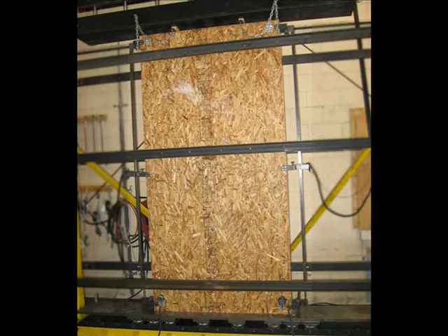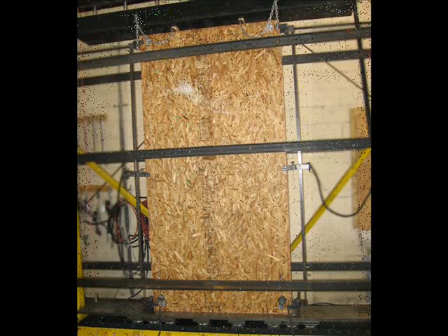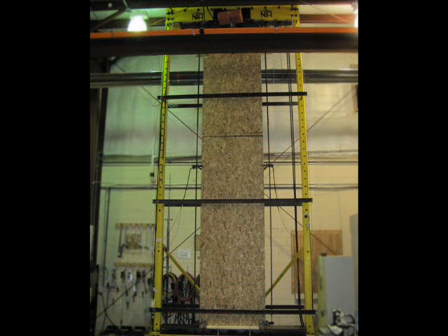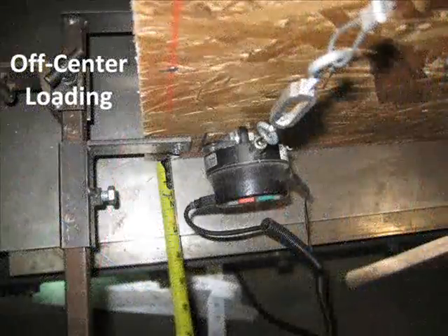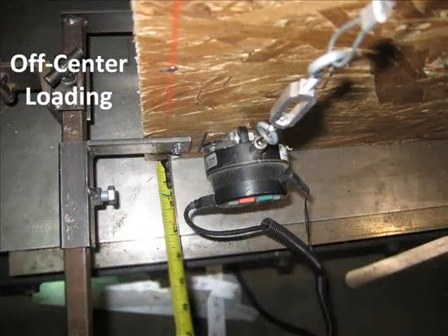of the first story. The test method requires the testing of 3 identical specimens constructed to represent the construction and height encountered in service and having a nominal width of 4 feet. A uniform load is directed through a continuous beam to the top of the wall assembly, which is slightly off-center to produce a bowing of the wall and panel.